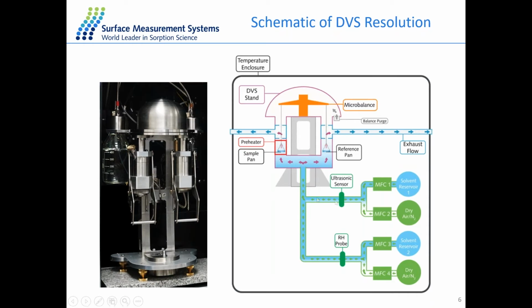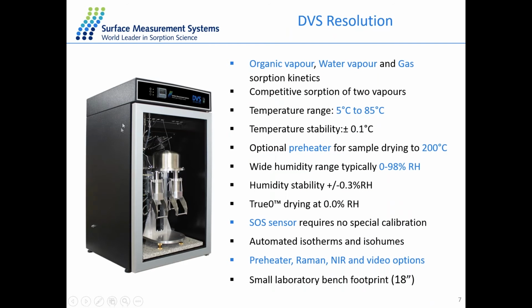And then this mixture will flow to both the sample chamber and the reference chamber at a constant rate. The sample inside the chamber will pick up the moisture, and the mass change will be detected by the balance here. The whole stand like this one sits in an incubator with a temperature range from 5 to 85 degrees. That means we can perform the experiment between 5 and 85 degrees.